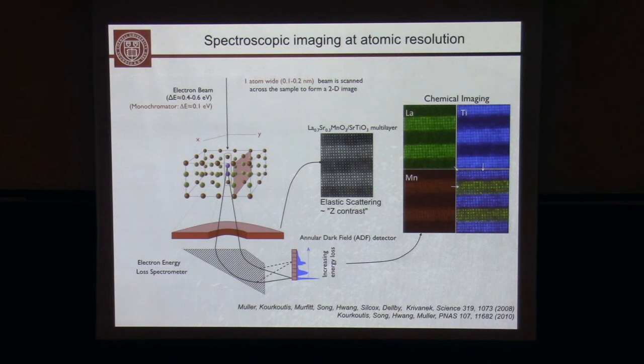So we can not only see where the atoms sit, but also which atom is sitting where. So here is this image decomposed into lanthanum, titanium, manganese. You see a purple line which tells you there's some intermixing between titanium and manganese. So this is really nice. It tells some of the physics. We are really interested in bonding variations.